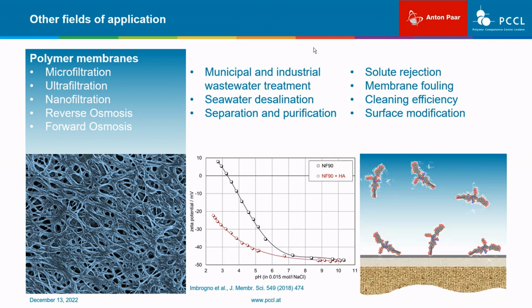The addition of a certain concentration of humic acid to the aqueous solution alters the evolution of the Zeta potential with pH and confirms the adsorption of these acidic entities on the surface of the membrane. Adsorption of humic acid may be unexpected since both the membrane surface and this macromolecule exhibit a negative charge. But remember, hydrophobic interaction may apparently exceed the electrostatic repulsion, thereby leading to a certain deposition of humic acid molecules that render the membrane surface more acidic.